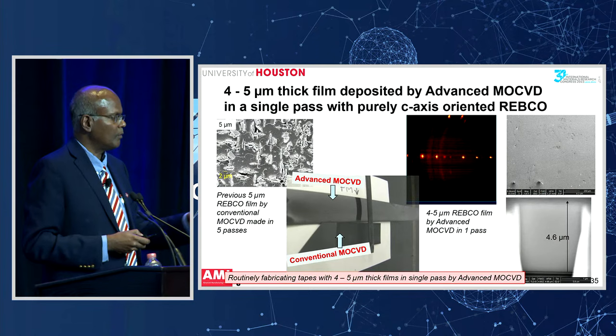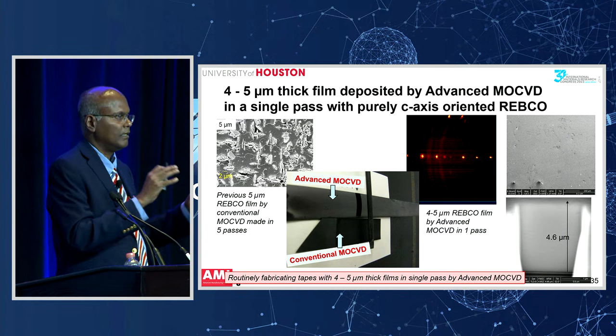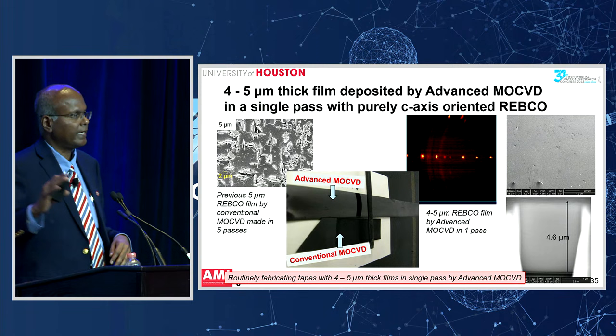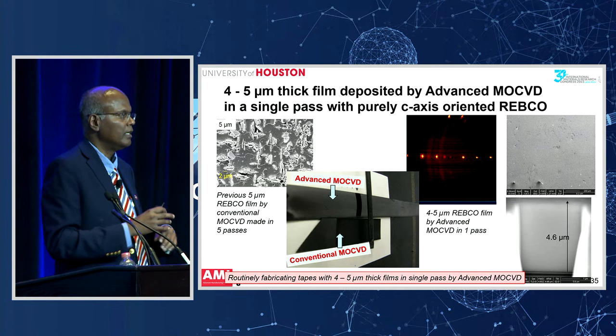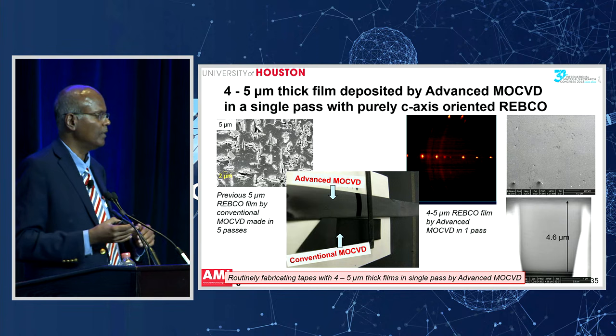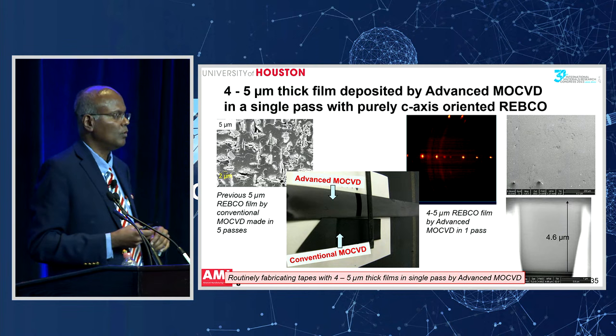You can see on the left side what I showed you before with the conventional MOCVD process, several misaligned grains when you try to make the films thicker. On the rightmost side, you can see the film made by advanced MOCVD, a 4.6 micron film, is totally featureless. You don't see any kind of structure because it's a very high quality epitaxial film. You see in the X-ray diffraction also, all the 00L peaks, and there are no misaligned grains in the film.